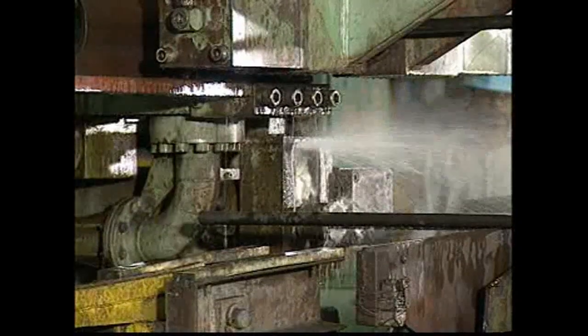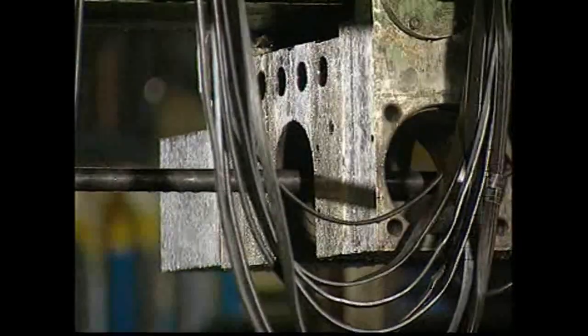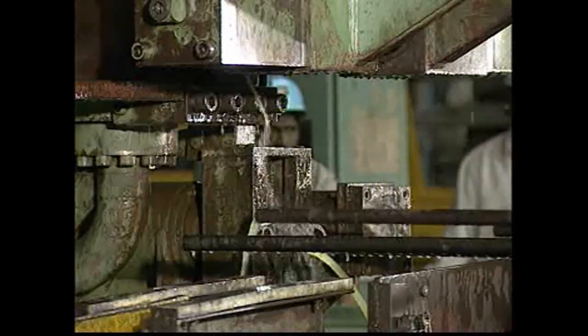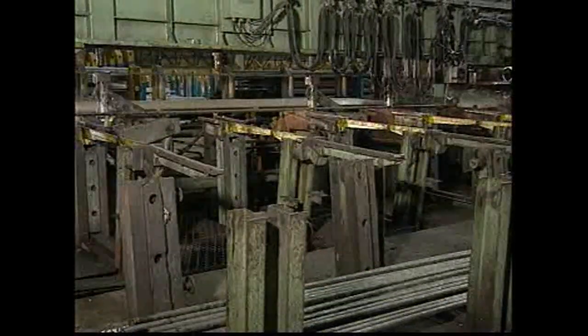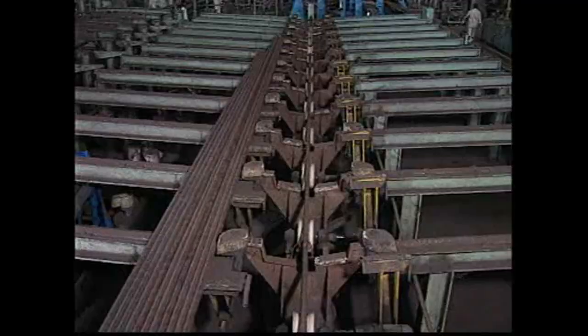Tubes are hydrostatically tested as per code and customer requirements. Tubes are also non-destructively tested for surface and subsurface defects, adopting eddy current and ultrasonic methods. Visual and dimensional inspection are also carried out on 100% of the tubes.